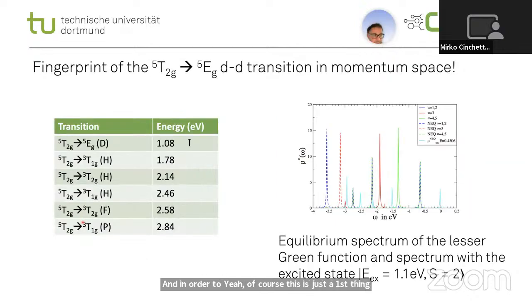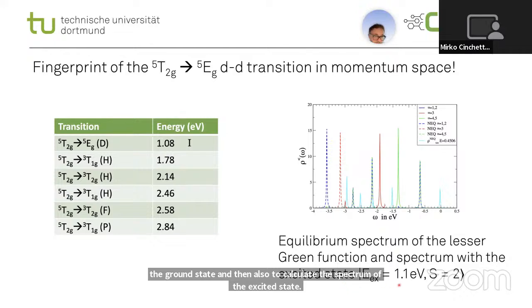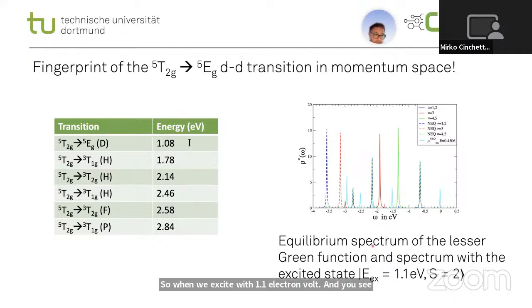So we asked our colleague, Fridtjof Anders here at TU Dortmund, to calculate the equilibrium spectrum of the lesser Green function, which basically corresponds to what we would see in an ARPES experiment from our iron 2+ multiplet in the ground state, and then also to calculate the spectrum of the excited state, when we excite with 1.1 electron volt. And you see that basically many of the peaks of these two Green functions overlap. So this gives us another argument to expect that what we see in the ARPES for the ground state and for the excited state looks the same.